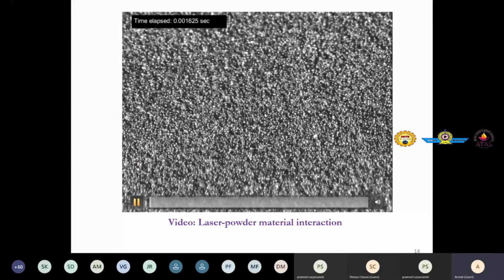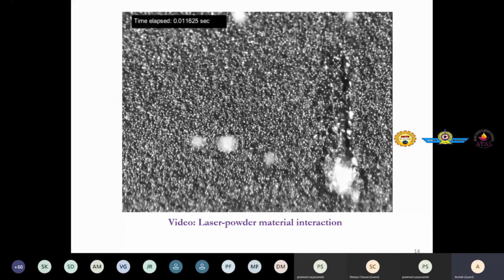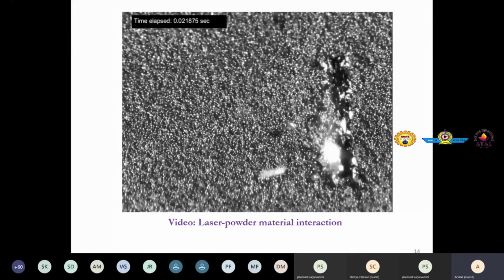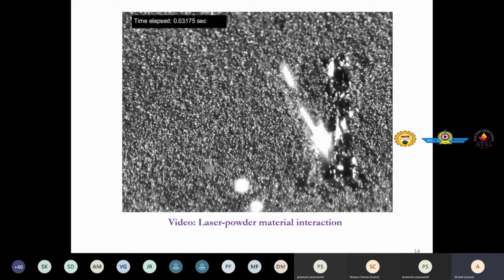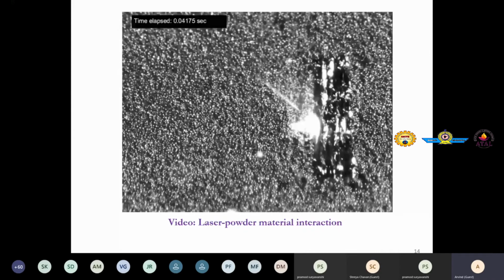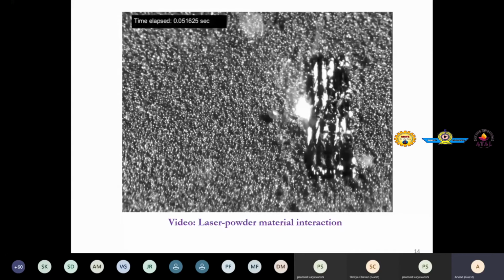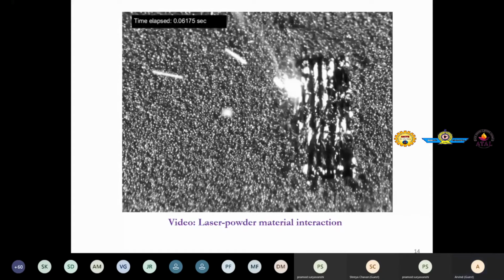So I would like to show you another video of how the laser interacts with powder. You see in the layer several micron size powder particles are there, and when the laser is impacting and traversing along the designated tool path, local melting and resolidification happens, and the melt pool consolidates into a solidified layer. And it happens so quickly. You can see the real time involved there in the video.